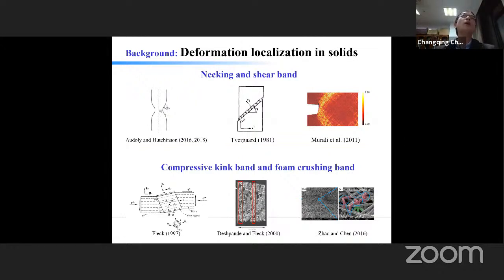As the topic of this talk is mechanics of materials, people in this field are always concerned about the failure of solids or the failure of the material. We know in most cases the material fails by localized deformation. Say for a low carbon steel, if you load it in tension, you are able to observe necking behavior. If you compress a medium to high carbon steel, you will see a failure in the form of a shear band. If a crack is present, you will see the crack grow along these two directions.